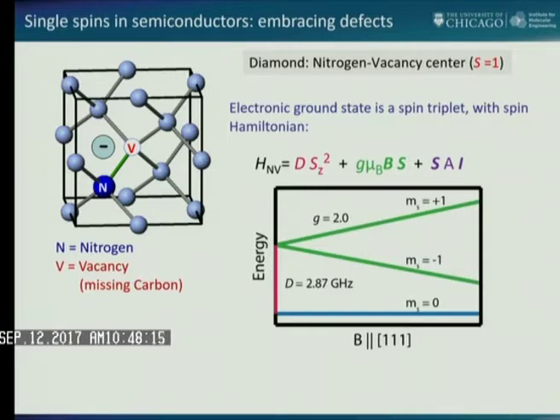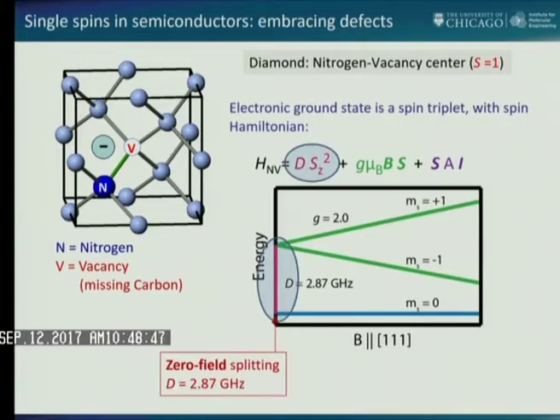The first is that these defects in a material like diamond, for those of you who are familiar with magnetism, normally to separate an electron going between spin up and spin down, you need to apply a magnetic field, right? The magnetic field creates a Zeeman splitting. What's interesting in these materials is that there's a lot of strain in the lattice, and the strain lifts that degeneracy automatically. So even with no magnetic field, you can address the spin up and the spin down state. So it's even easier. You don't need to do anything other than look at these quantum states to begin to explore them. And the natural splitting that comes from the strain is 2.8 gigahertz.